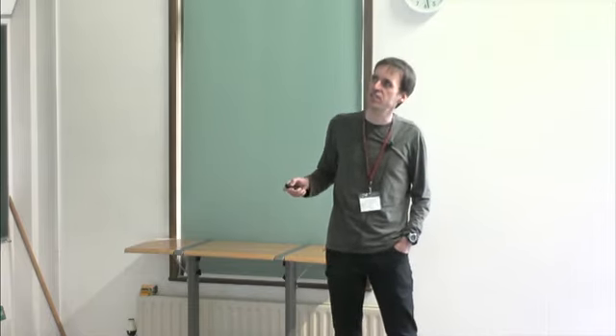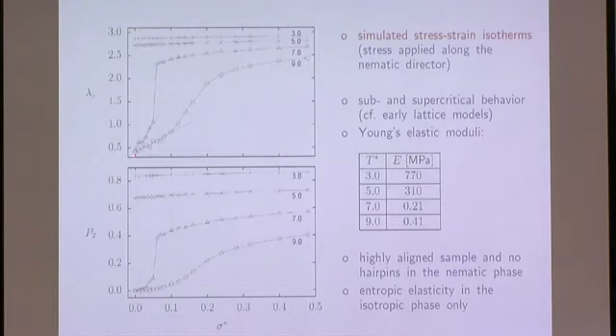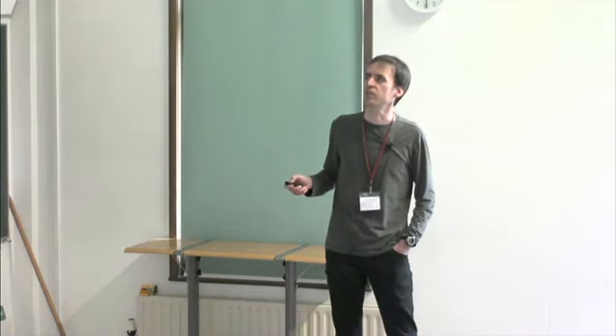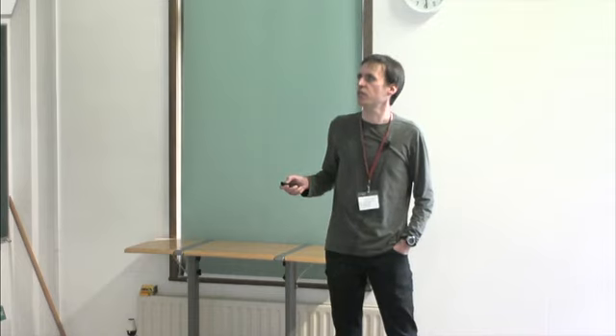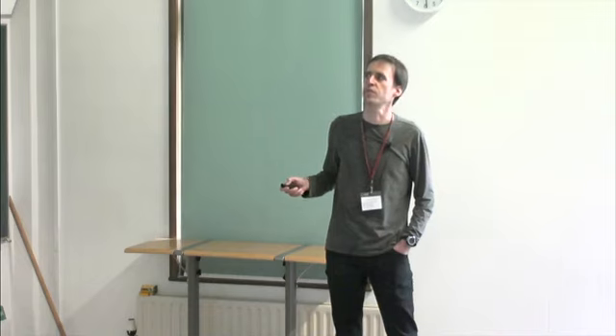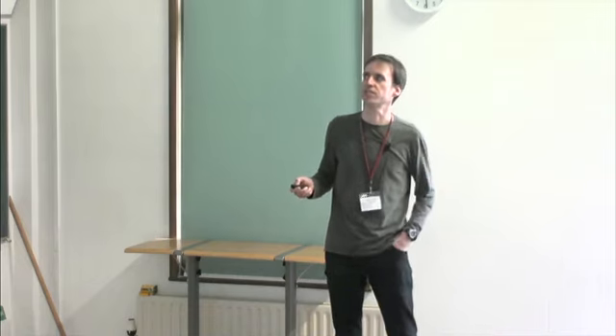What's also interesting here is that one can estimate the elastic moduli, and it turns out that in the nematic phase they are really high, even higher than experimentally predicted. But anyway, if you have your sample already very aligned, on pulling you just deform the FENE bonds a little bit, and that's it. However, in the isotropic phase we get much lower values for the Young modulus, and more importantly, the modulus increases with increasing temperature. So we believe that this is the signature of entropic elasticity.